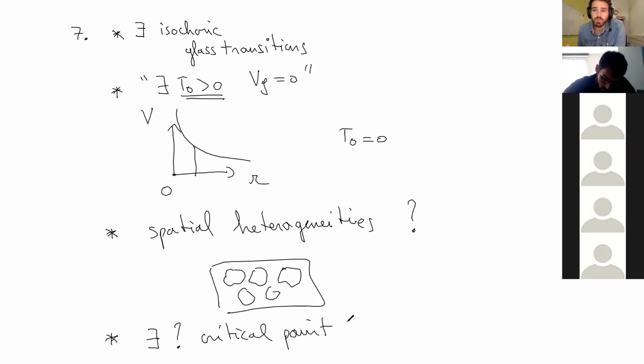And of course, the free volume picture, which is purely dynamic, kinetic, dealing with metastable states of matter, cannot address those equilibrium transition points. And so there are plenty of researchers, including at ENS in Paris, for instance, who are really trying to reveal the existence of this underlying phase transition. And the problem with free volume is that this doesn't help at all. So you see, you have plenty of criticism, and you should be aware of that when you deal with the free volume picture and cooperativity.